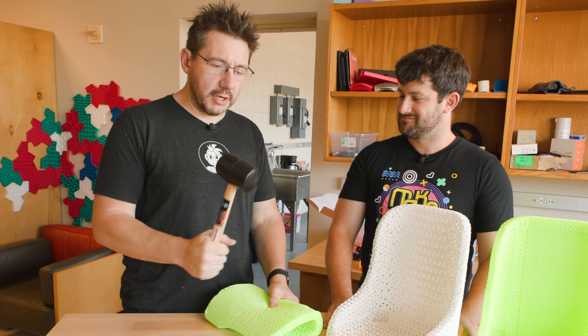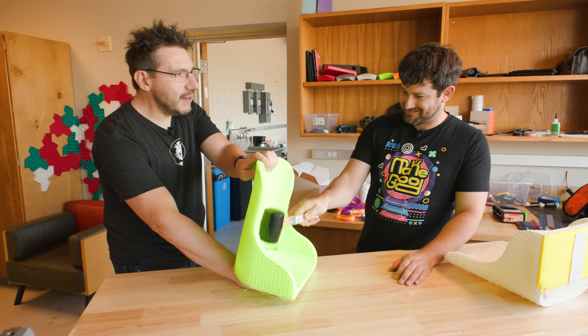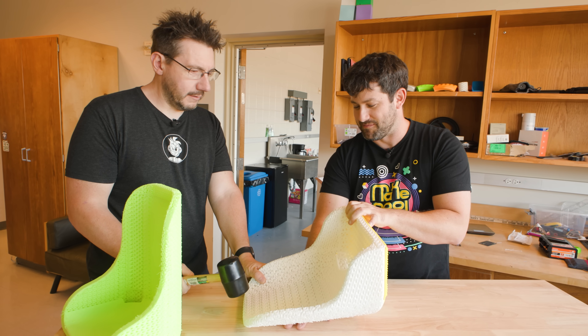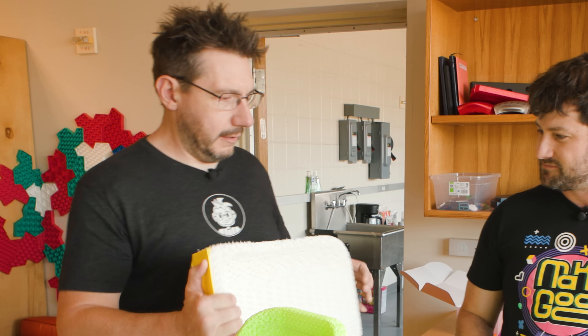These are soft, cushy, comfortable, but they serve a purpose — one way we could test their squishiness would be if we hit each other in the hand with a mallet. Bring it on! Oh, that's not bad. Hit him harder! It's doing a good job. Now the white one — I can barely feel it. It really bounces the hammer back, does a good job deflecting the force and dissipating it. The gyroid surface also helped deflect the force. Using different densities of infill and different numbers of shells, you'll get different properties — it's really up to you.